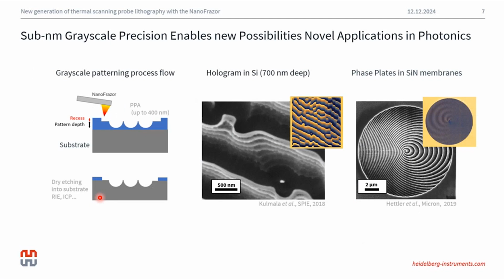So going back again to our example of grayscale lithography, here you could see the output of this writing method from the NanoFrazor. On the right-hand side, we have the topography image, which is readily generated from within our NanoFrazor system. And on the left-hand side, we see the SEM image of the final created feature here in silicon and here in silicon nitride for creating phase plates. In both cases, the PPA itself was used as a mask to transfer downwards onto the material of choice.